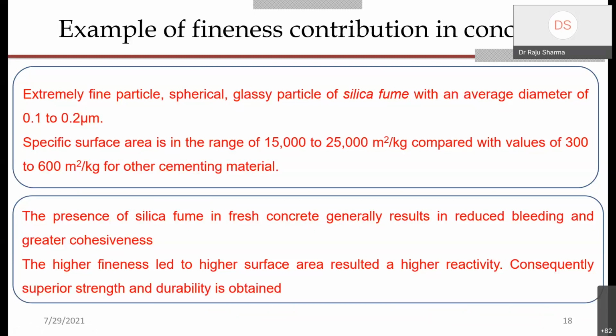If you have some results, how can you give these reasons? The presence of silica fume in fresh concrete generally results in reduced bleeding and greater cohesiveness, right? The higher fineness of the silica fume led to the higher surface area, which resulted in higher reactivity. Consequently, superior strength and durability is obtained, right? But this higher reactivity, being a researcher, you cannot conclude without looking into the chemical composition of this particular product.